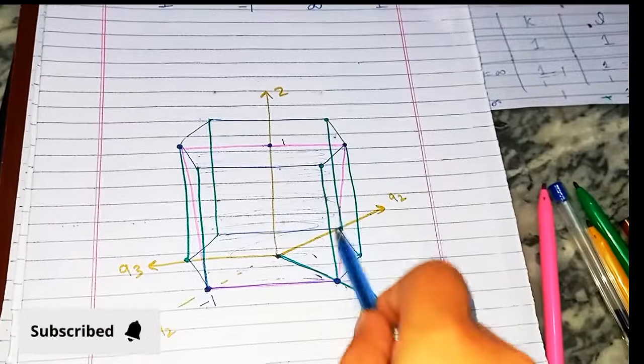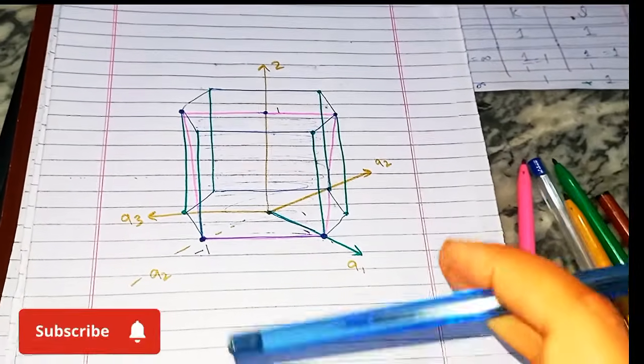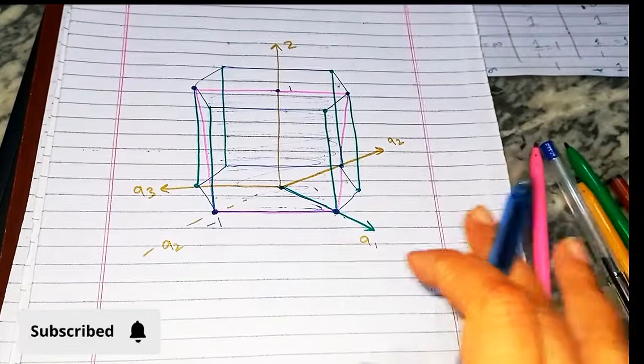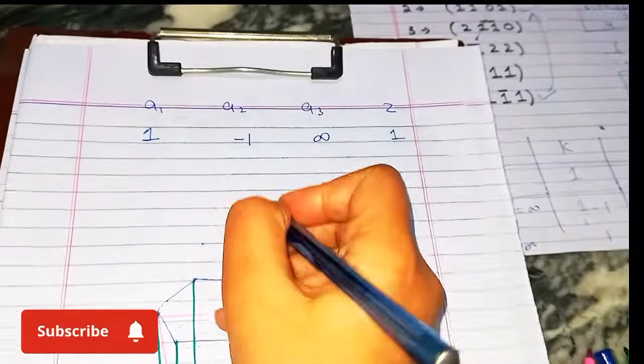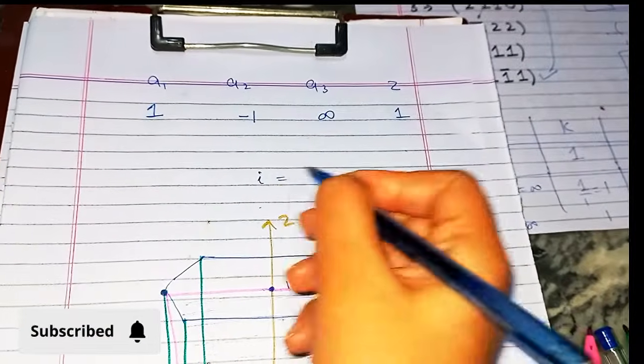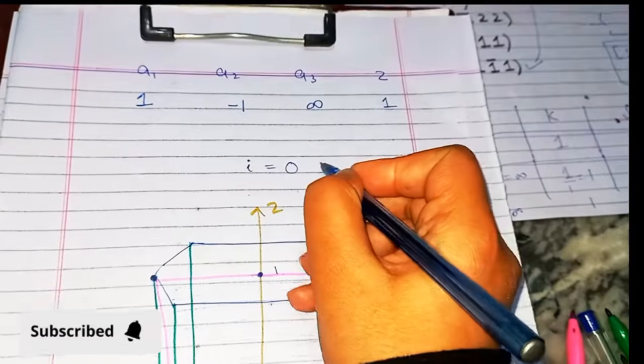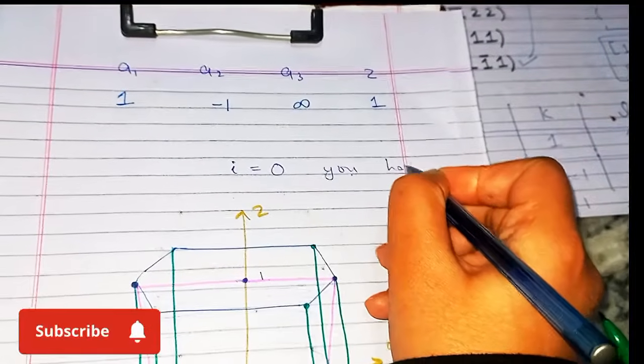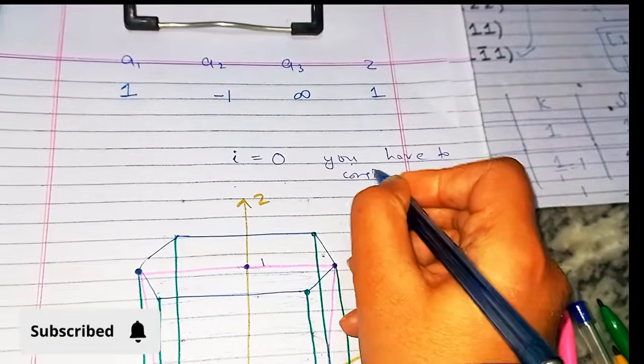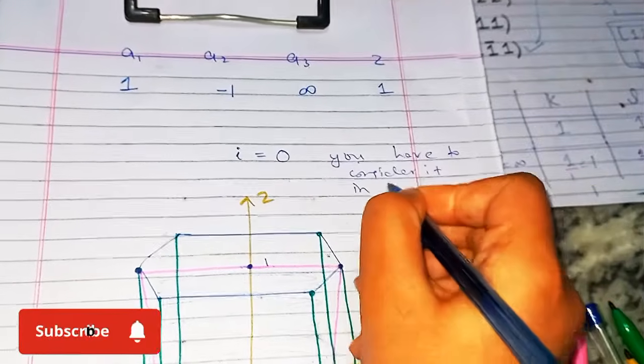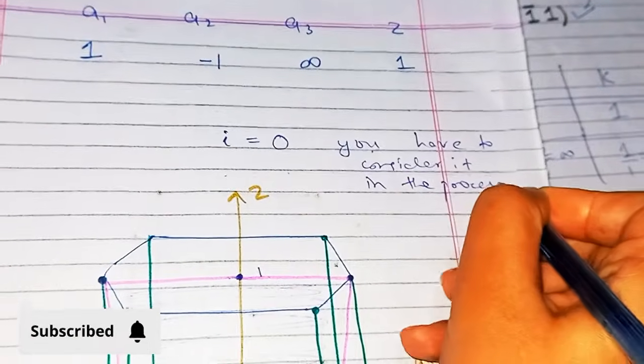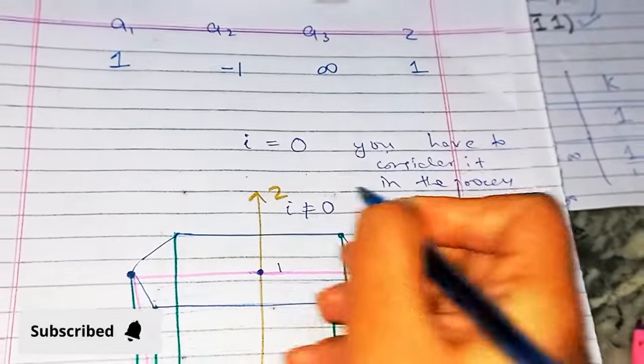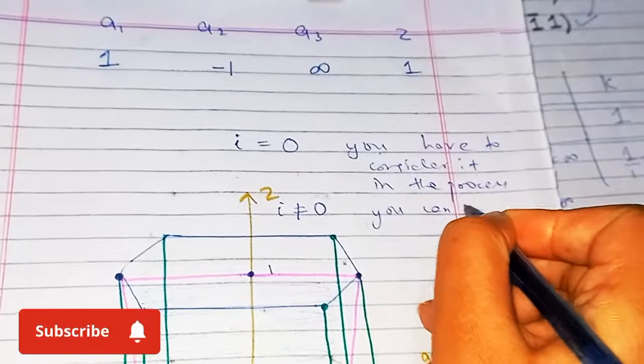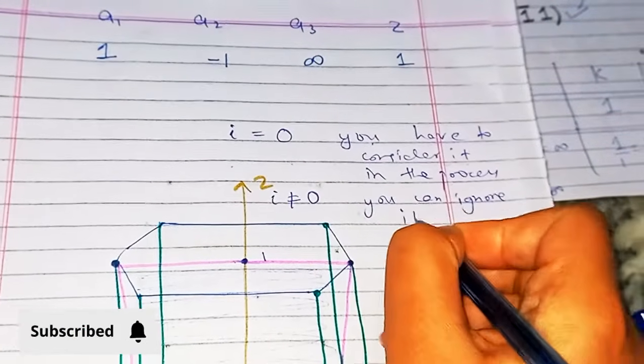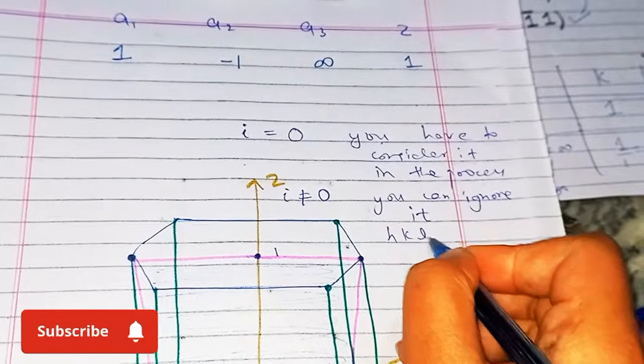So that is it for this video. I hope you got it, and you must remember these hacks. Whenever I, which is the index, is 0, you have to consider it in the process. Whenever I is not equal to 0, you can ignore it and play with HKL only.